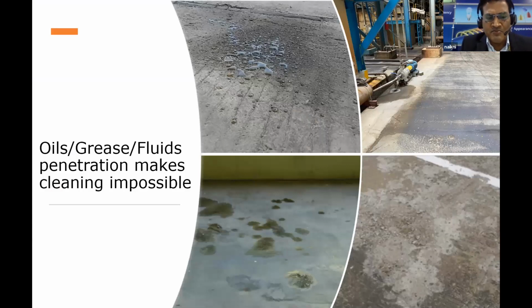These images, I'm sure many of you must have seen from time to time, but you can see here, these are floors that have not been painted for some reason, but the level of contamination that exists on these floors, whatever you may try and remedy, rectify or create a process to clean up these floors and then repaint them, you are never going to be 100%, because these floors over a period of time have absorbed so much of oils, battery fluids, other natural salts, moisture, so that penetrates deep into the concrete. It's almost impossible to make them back to its original level. So you can only come to a level that is acceptable, but it'll never be 100% or perfectly fine with the new coatings.